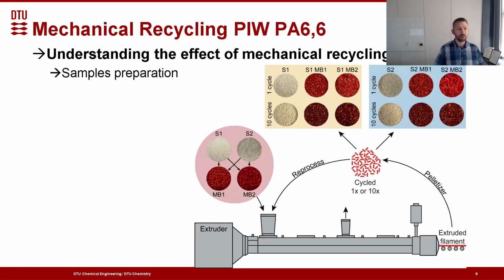The mechanical recycling in this case was done through an extrusion process, where you can see here that supplier 1 was run for 1 and 10 cycles. Then we combined supplier 1 with master batch 1 and with master batch 2, and also ran them for 1 and 10 cycles. Similarly, for another supplier, we did exactly the same samples. Reprocessing, where this was cycled repeatedly through the process to obtain an extruded filament, which was pelletized and then used again and again. This allows us to get an insight into what happens in the recycling step.